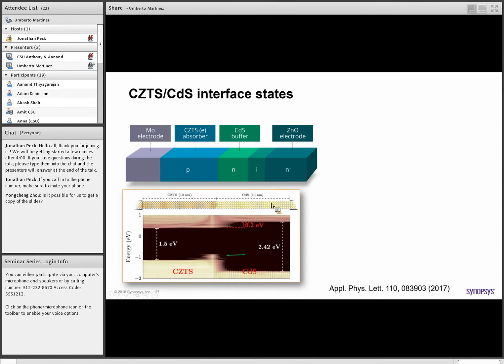So now I already showed the results, this plot that you now should understand very well. This is energy, and again, in this dimension, we go all the way across our device. You see that you have 10 nanometers and 10 nanometers for the two materials. This is a semiconductor interface, so you're not limited to metal-semiconductor interfaces. Let's analyze this specific plot in a little more detail. We can see that we calculate a conduction band offset of about 0.2 eV, which is fairly good. You would expect a pretty good performance by just checking these parameters.